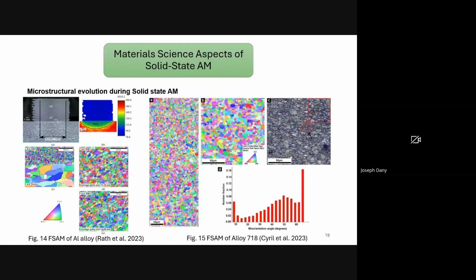The specific type of DRX mechanism, dynamic recrystallization mechanism, operating is strongly influenced by the stacking fault energy of the material. For example, aluminum alloys, as I said earlier, which have a relatively high stacking fault energy, typically undergo continuous dynamic recrystallization. In that process, the dislocations rearrange into subgrains, and with progressive strain, these subgrains gradually rotate and transform into new strain-free grains.